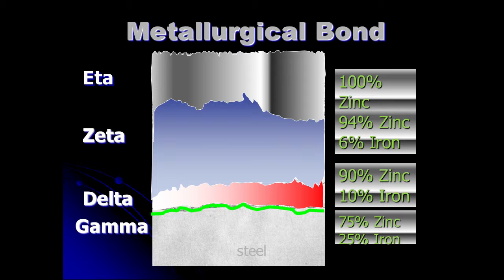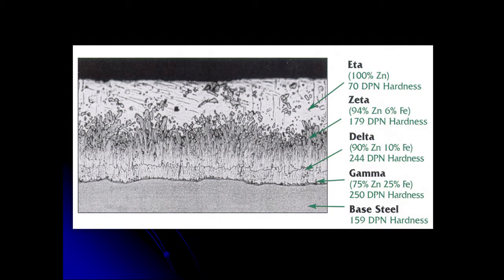Your zeta is 94/6, and your last is your 100% pure zinc. You don't have to worry about moisture coming underneath the coating and popping and peeling it off. It's part of the steel. If I took a Band-Aid and put it on the back of my hand, that's like metallizing or paint. It's a mechanical bond. Hot-dip galvanizing is like your skin. It's actually part of the steel, so you're not going to pop or peel or chip it off.